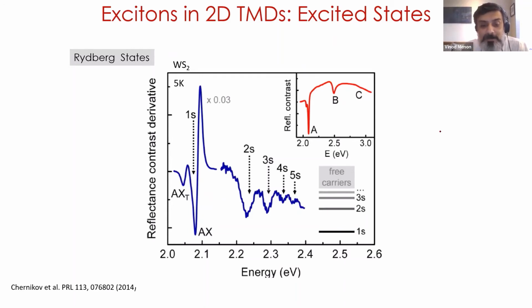And this is something that has not been studied much in other inorganic semiconductor systems, simply because the binding energies are not very high, and so you can't see it. The only exception to this is cuprous oxide, where people have seen it, but there the oscillator strengths are not very large.